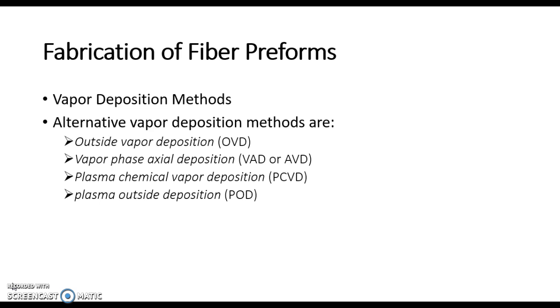The plasma chemical vapor deposition (PCVD) uses deposition inside a tube similar to MCVD. However, microwaves instead of a burner are used for heating the deposition region. The deposition is slow but very precise. A modified method with particularly high deposition rate is plasma impulse chemical vapor deposition, where short microwave pulses are used. There is also plasma enhanced chemical vapor deposition, operating at atmospheric pressure with fairly high deposition rate.